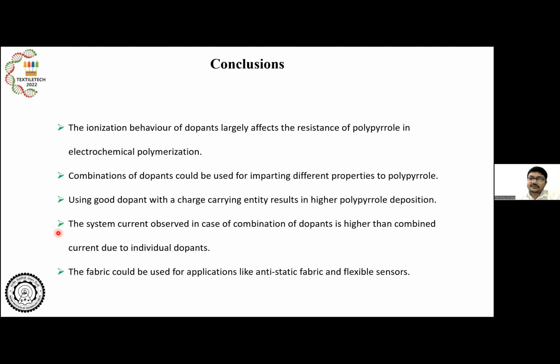Then the system current observed in the case of the combination of dopants was higher than the algebraic sum of the currents observed due to the individual dopants, which is good for polymerization. Lastly, the fabric could be used not only for anti-static applications, but we are also trying to develop some flexible sensors based on this polypyrrole coated fabric.